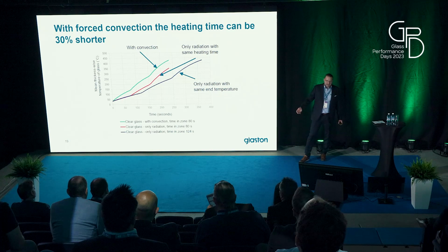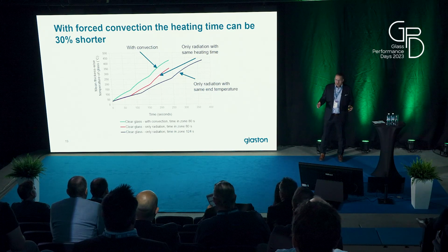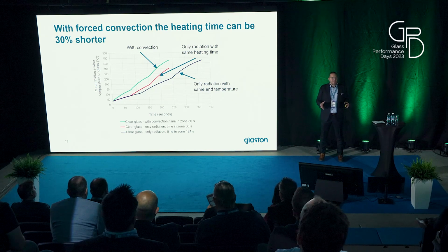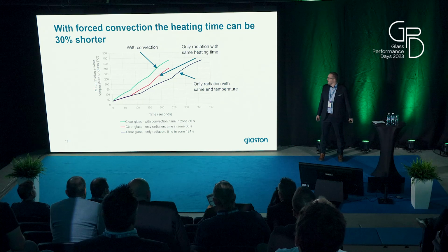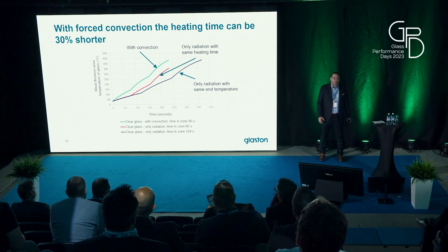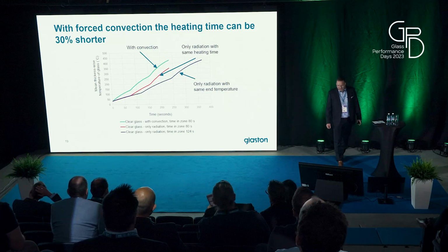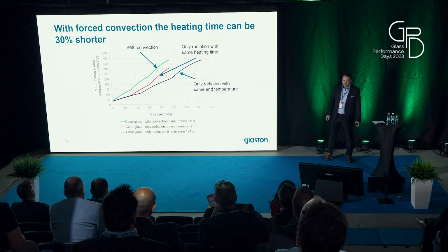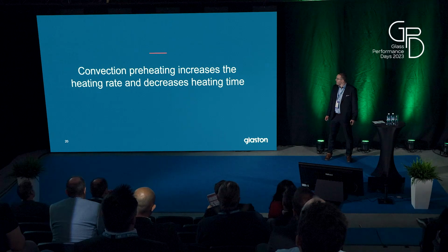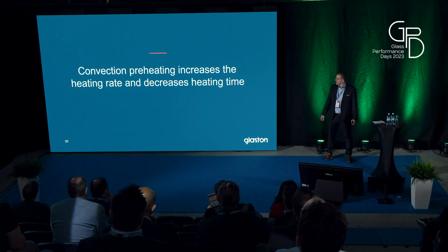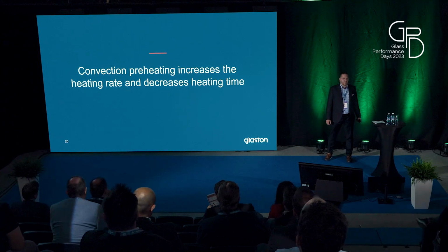And this is also leading to the idea that maybe we can make the automotive line shorter. We don't have to use so many preheating chambers in the process. So that was one extra benefit for convection, that we can increase the heating rate and decrease the heating time.